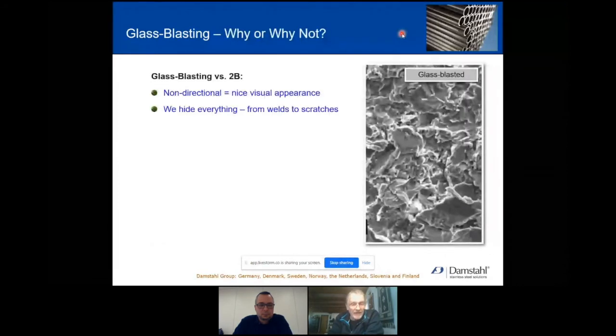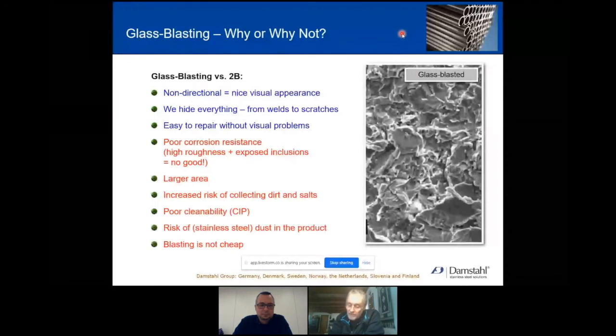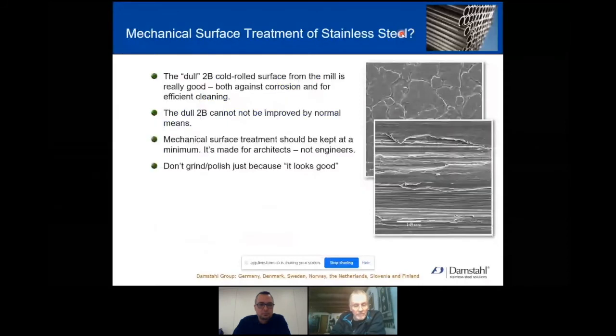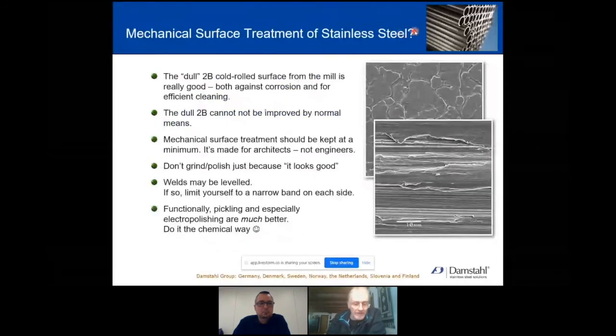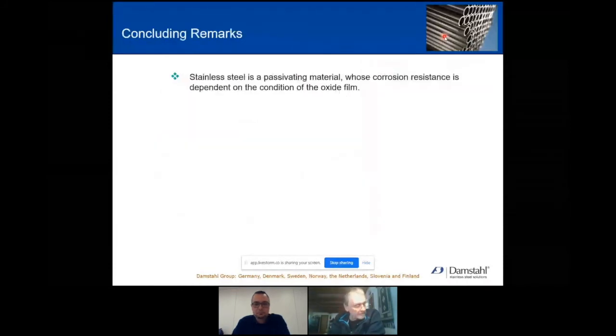So basically, it's electro-polishing. That's definitely perfect. Otherwise, if you can't afford electro-polishing, then don't do anything at all. So my time is running out. I'm sorry about that. Basically, chemical surface treatment is actually so much better than any mechanical surface treatment, unless using a very, very fine polishing.